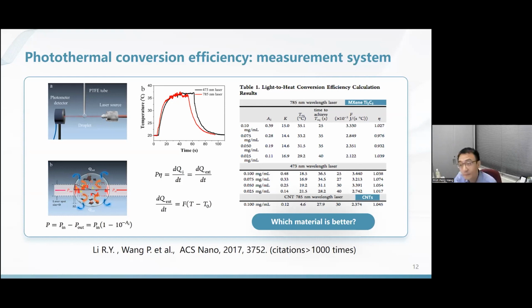Now, the results may be surprising or maybe not surprising for you. The results say that those two materials both have very high photothermal conversion efficiency. Both are close to 100%. So the conclusion we get from this measurement system is that very expensive, fancy material is not necessarily better than those common, conventional, cheap materials. All right, what implication do these results tell us? I'll leave that to you.